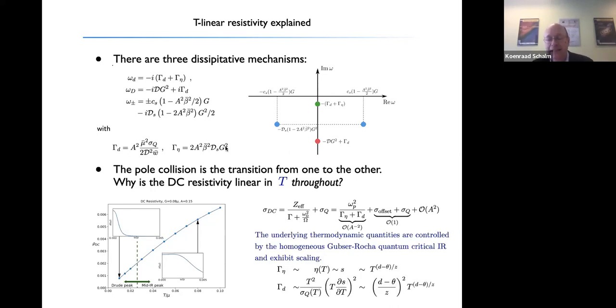Now, the underlying reason that you still get a linear in T resistivity is that the temperature dependence of each of these combined systems is actually determined by the fact that you flow to this quantum critical IR, this near AdS2 physics, or this Z infinity fixed point. They fix a lot of these scaling properties. You know, the entropy density is not a free parameter. It must scale as T to the D minus theta over Z in these systems. And in these two systems, if you take a generic one of these Lifshitz hyperscaling violating fixed points, they scale like this. So they